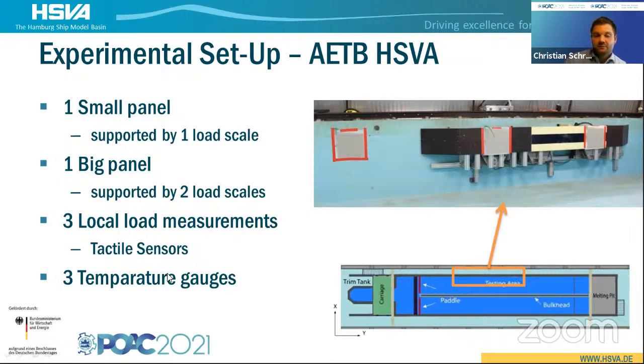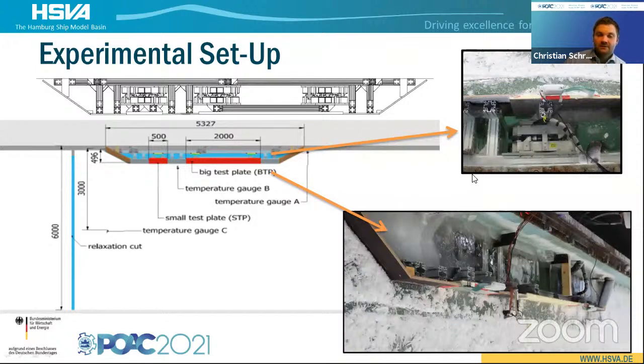Next to that, we had 3 temperature gauges on different locations. You can see the setup a bit more here in ice conditions on this slide. We had 3 temperature gauges, one a bit further away from the setup and 2 relatively close to the setup to measure the temperature profile over the ice thickness. Our target ice thickness during the tests was always 20 centimeters to have a fixed variable during the testing, and we varied, for example, the salinity of the ice.